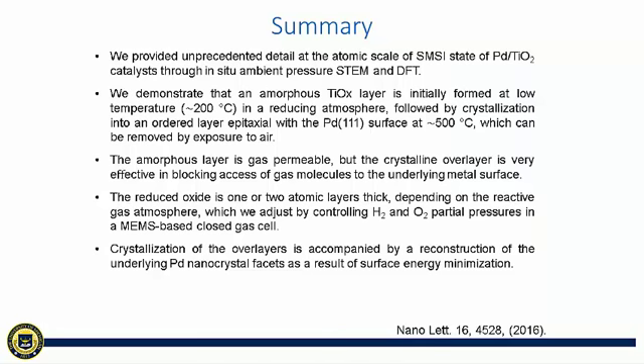Here is the summary of this project. We provided atomic scale detail of the dynamic process of the SMSI state of the palladium TiO2 system through ambient pressure TEM and DFT calculation. We found that an amorphous TiOx layer is initially formed at low temperature in a reducing atmosphere, followed by crystallization into an ordered epitaxial layer on the palladium 111 surface at 500 C. The amorphous layer is gas permeable, while the crystalline overlayer is very effective in blocking access of gas molecules to the underlying metal surface. The reduced oxide is 1 or 2 atomic layers thick, depending on the atmosphere. Crystallization of the overlayer is accompanied by a reconstruction of the palladium nanoparticle as a result of surface energy minimization.